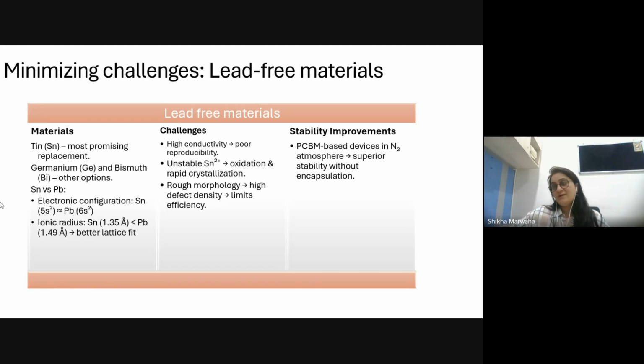For lead, I just said that lead is quite stable, but for tin it's quite unstable, because tin gets converted to Sn2 positive, so it becomes an ion, and it leads to oxidation and rapid crystallization. So that is something that is not acceptable. Still work is going on. And they have a quite rough morphology, they have high defect density, so because of that the efficiency is quite low.